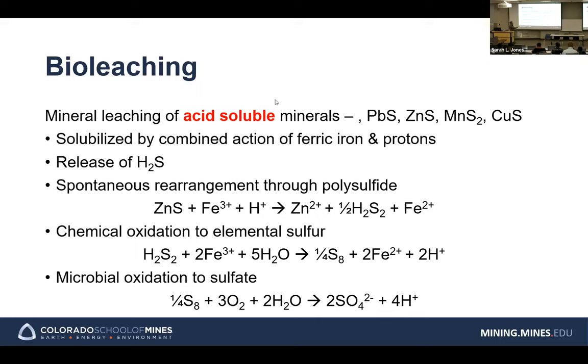So one example is zinc sulfide, sphalerite, reacted with the ferric ion and also H plus, an acid. And a zinc 2 plus cation will be formed, and H2S to polysulfide. And again, Fe3 plus becomes Fe2 plus. And then other reactions could happen. So biooxidation is only for the sulfide, such as pyrite. But bioleaching is we oxidize the sulfide, and at the same time, we have the value metal in the solution. Okay, so if it is zinc sulfide, we have the zinc. If it is copper sulfide, we get the copper in the solution.